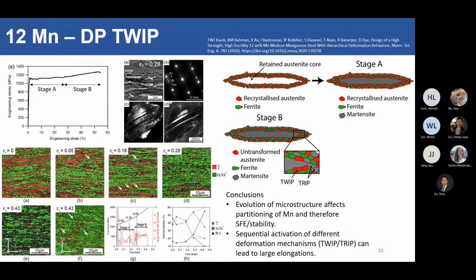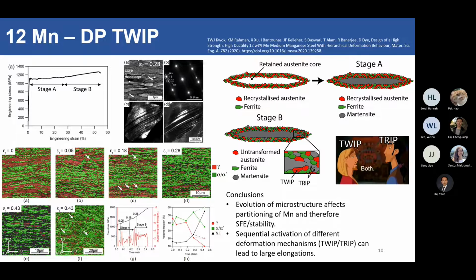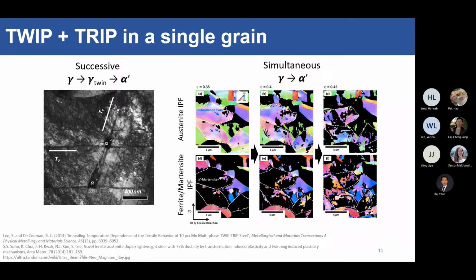But more importantly, we can actually use the TWIP and the TRIP mechanisms together to give you very large elongations in medium manganese steels. Right, so this TWIP plus TRIP mechanism we found is really, really good, but we want both of them to occur together in the same grain. We don't want some grains to be TRIPping and some TWIPping, and that gives you this very horrible serrated tensile curve. So that's not very good for metal forming purposes. So we want TWIP and TRIP to be occurring within the same austenite grain.